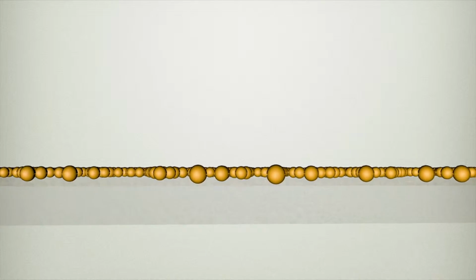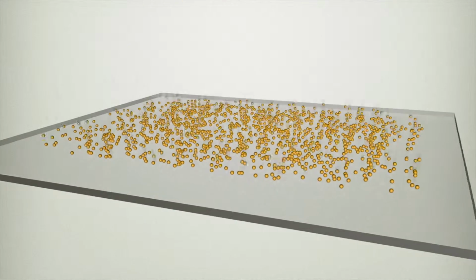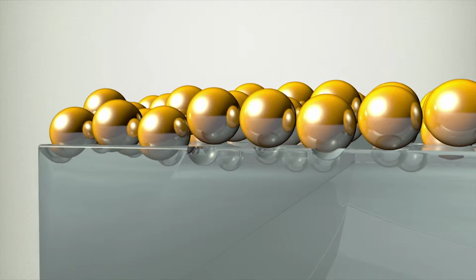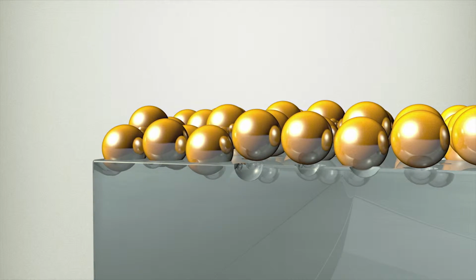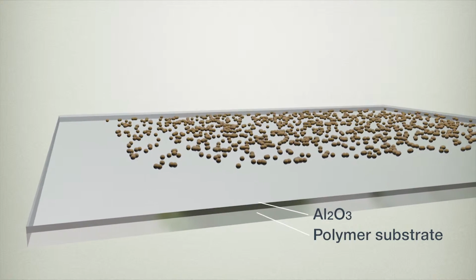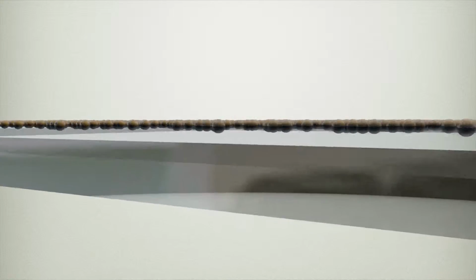Common barrier coating technology that deposited a silicon oxide thin film on the polymer substrate using the PECVD method has a disadvantage of generating fine protrusions on the surface due to plasma damage, which deteriorated barrier properties. On the contrary, the barrier film manufactured by this technology has a smooth surface, and the barrier property is also excellent, as the aluminum oxide layer formed on the polymer substrate by the sputtering method protects the substrate surface from plasma damage.